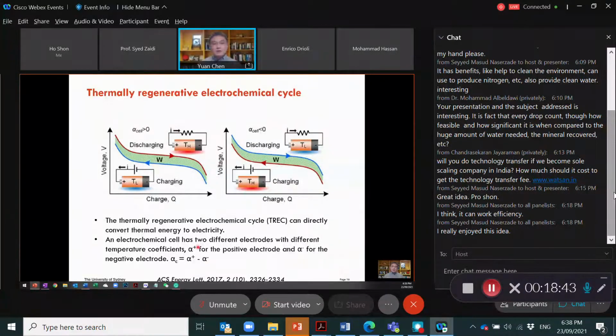Now, if we have a cell built with two electrodes, and they have a temperature coefficient which is larger than 0, then we can actually do the discharging of the cell at a relatively high temperature here. And this is the amount of the energy that will be released. And then we can charge the cell by lowering the temperature of the electrolyte. And here is the charging, and this is the energy you need to charge the cell. So the difference between the discharge and the charging, this green shaded area, is actually the electricity that can be generated from the whole cycle.